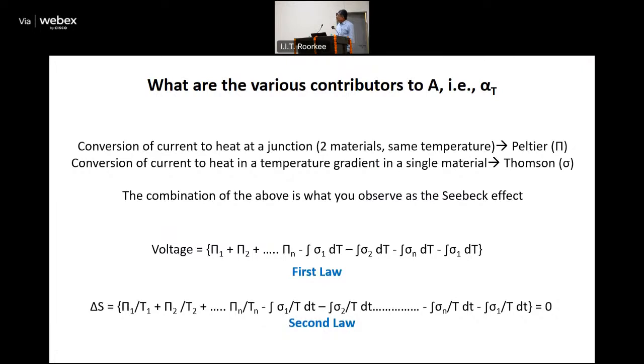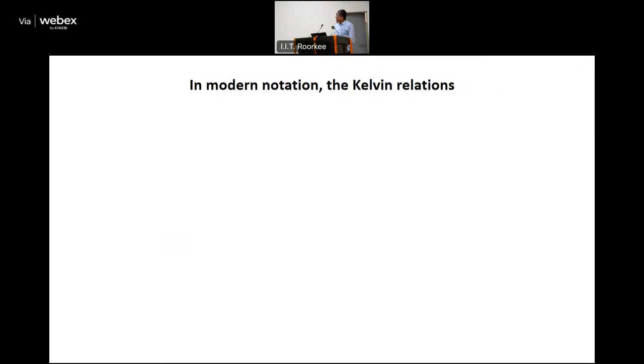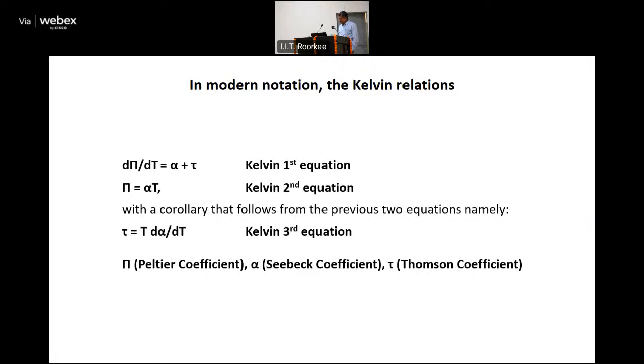And if you now take these large numbers and reduce them to just two metals, you will recover what I call the Kelvin relationships in thermoelectricity. So this is the first equation, which tells you the temperature derivative of the Peltier effect is the Seebeck effect plus the Thomson effect, the Thomson coefficient. And the Peltier coefficient itself is alpha t.